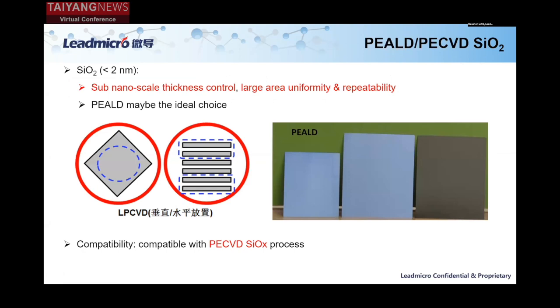The reason why we choose the silicon oxide using PEALD and PECVD is very simple, as just explained. The tunnel oxide thickness is very thin. How to control this thickness in sub-nanometer scale proactively, and with the large area uniformity and repeatability required for mass production, probably ALD is one of the ideal choices. As well, you can see the right-hand image here. Even with G12 size wafers, we can do the deposition very, very uniformly. As our PEALD technology is built on the PECVD platform, obviously it is compatible with the PECVD silicon oxide process.